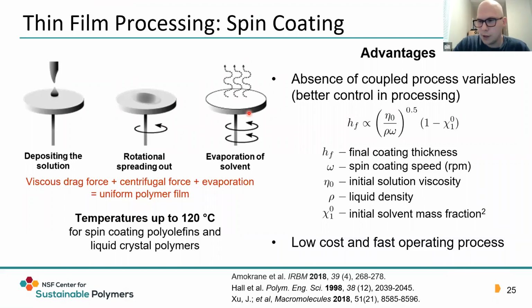So it's great to be here with you all to be able to talk about some film processing. So often when you create a material, you want to characterize it in the solid state. It's very frequent you want to make it out of a film. And one of the easiest ways to do that is to dissolve it in some compatible solvent and then spin coat it, where you use a high-speed rotating substrate, and then the solvent evaporates, leaving behind your polymer film.